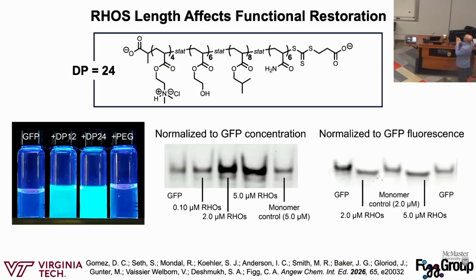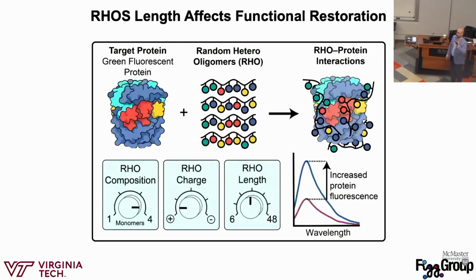In this case, we normalized to GFP fluorescence, so we essentially calculated how much GFP to load with the random heteroligomers, where all the bands would be about the same intensity. And if we normalize to GFP fluorescence, in the presence of the rhos, we actually see a slight shift in mobility, which also suggests to us that the rhos are binding to the protein surface and changing the surface charge, surface properties, so they move through the gel differently. So all of this suggests to us that the oligomers are interacting with the protein surface. We did a ton of other characterization to confirm that, but I skip over some of it for time. In the paper, there's a ton, so if you want more, look at the paper. So where we've gotten so far is that you can take this target protein with your random heteroligomers, and you can change composition, charge, and length, and increase fluorescence.